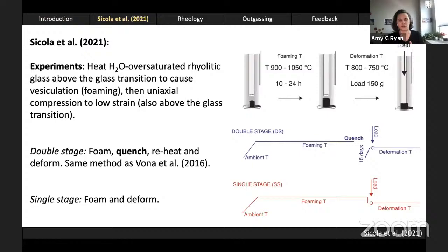Stefania Sicola completed her PhD at Roma Tre, and in her PhD she was studying the viscosity of bubbly melts. In these experiments, she would heat a water-oversaturated rhyolitic glass above the glass transition. That would cause it to foam, so to vesiculate and be populated with bubbles. And then she would compress the material under a small load to relatively low strain. She had two experiment subtypes, so-called double stage experiments and single stage experiments.